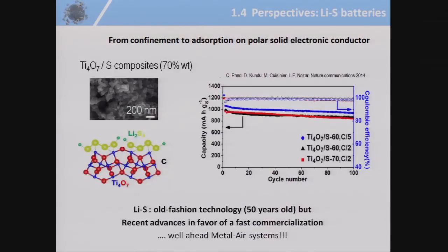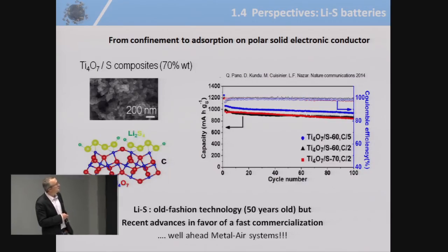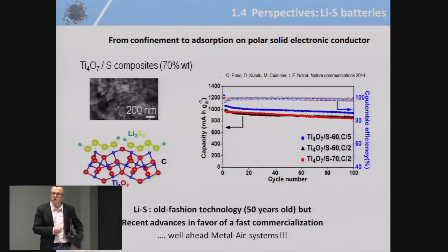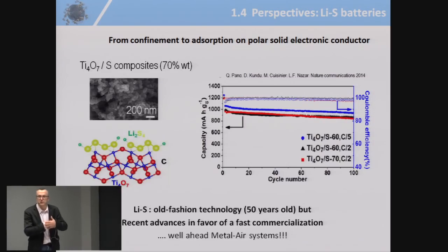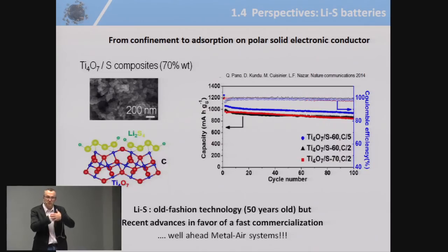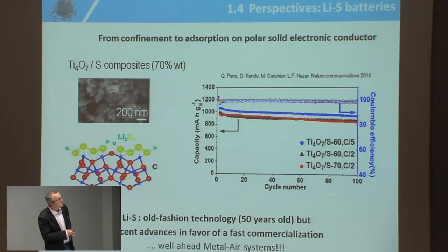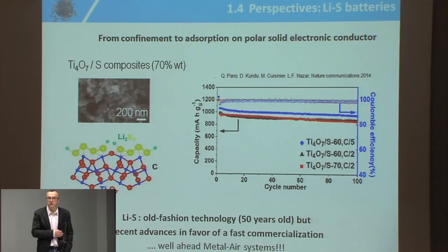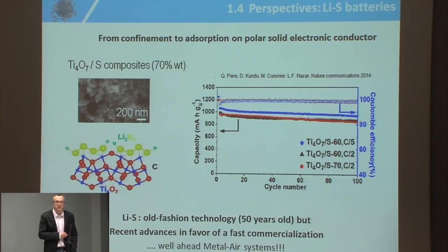But more, there is a recent paper here in 2014 that shows that if you take titanate material and put lithium sulfide on top of it, just by polarity you can really stack the lithium sulfur onto the titanium. And then you can block and trap the sulfur onto this kind of material. You have a look here, this is the cycle number, 100 cycles at 1000 milliampere per gram, which is quite outstanding for lithium sulfur. And this is one way to solve the cyclability issue of lithium sulfur.